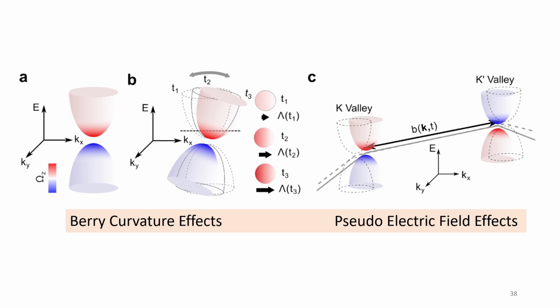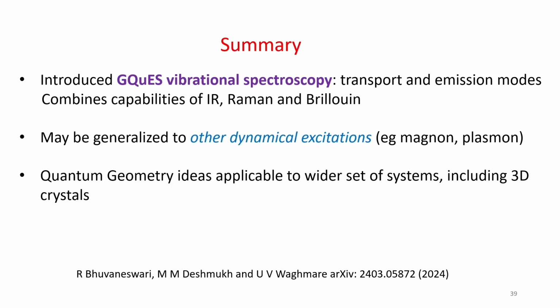Whereas if the distance between the two Dirac points oscillates due to the strain mode, that gives rise to a pseudo-electric field. And what the experiment showed is that you can have both of these effects in the twisted bilayer sample. And as a result, we show that both pseudo fields as well as geometry emergent fields can couple with each other and give rise to very interesting phenomena.